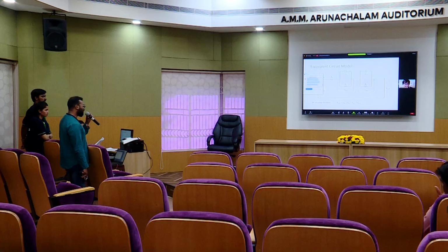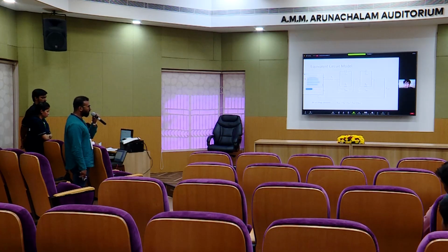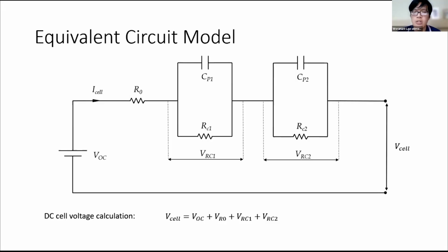Okay. Maybe you can try a third order or something, because I saw some graphs had some error in the SOH value, some predictions. Maybe the same data can be fitted to the third order, or there is no universality to it. That might help your predictions for SOH. There are some errors in cycling at higher cycles, like you showed in the results. Yes, sir. Maybe we can add another RC loop, and it will reduce the error. Also, for the equivalent circuit model, researchers usually try with EIS other elements like the Warburg element that represents diffusion or mass transfer. But using third order could maybe reduce the error of the test.